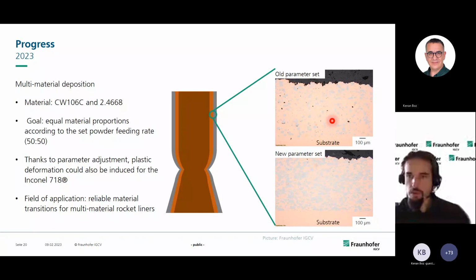And with the new parameter set, with a few adjustments, especially regarding pressure and temperature, we managed to plastically deform both materials, so the copper chrome zircon and the alloy 718, to get a rather homogeneous multi-material application of both materials onto a copper chrome zircon substrate.